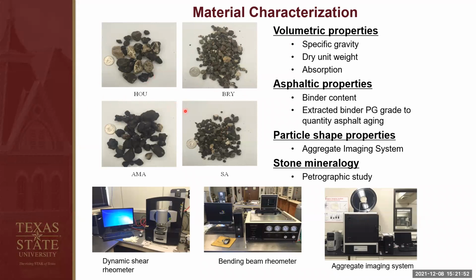So after we collected all the RAPs, we did a very extensive material characterization. We did a volumetric properties of the RAP. We measured specific gravity, dry unit weight, and absorption. We also extracted the asphalt from the RAP to measure the binder content. We also used PG grade to quantify the aging degree of the asphalt. And we also did some particle analysis. We did a particle shape properties using the aggregate imaging systems that we developed at Texas State University. And finally, we did some stone mineralogy testing using Petrographic Study.